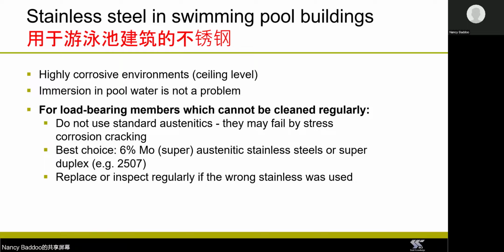So the general advice is that if you have a load-bearing member in an environment like this that cannot be cleaned very regularly, then you should not use the standard austenitics. You need to use a more highly alloyed stainless steel, perhaps a 6% molybdenum super austenitic or a super duplex, and very regular inspection should be carried out if the wrong stainless steel has been used.